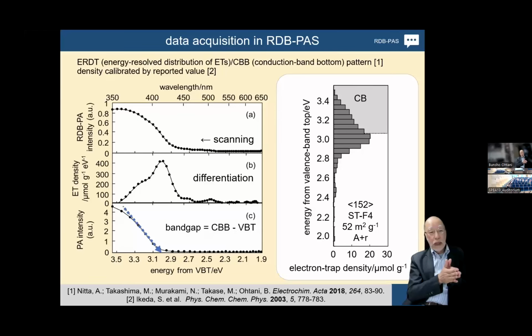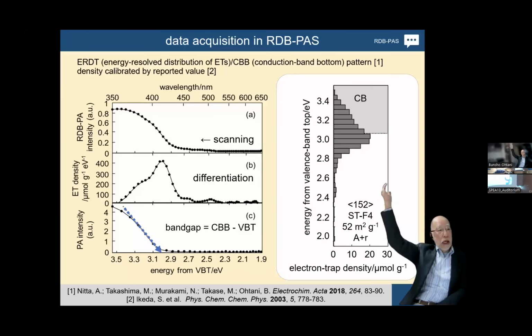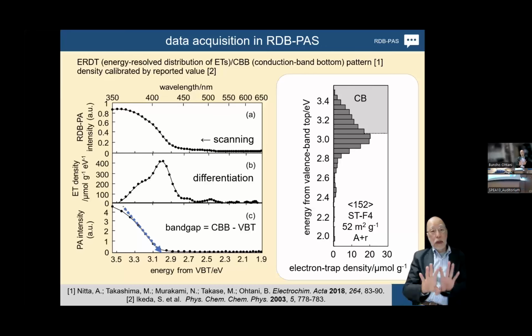From this, the band gap, that is the difference between the conduction band bottom and the valence band top, is obtained. Electron trap filling starts by the excitation from the valence band, so the energy of electron traps is shown as the difference to the valence band top position. Therefore, the electron trap distribution and also the conduction band bottom position can be plotted in the same figure. And 152 is the total density of electron traps.